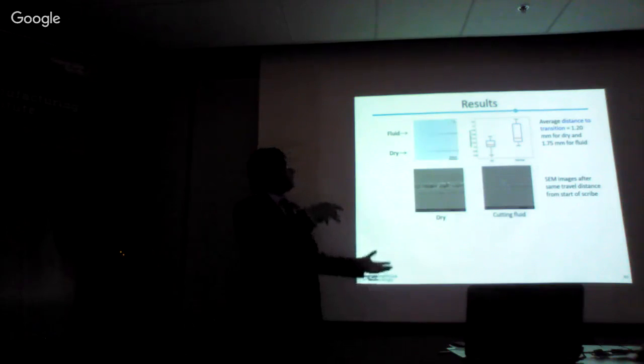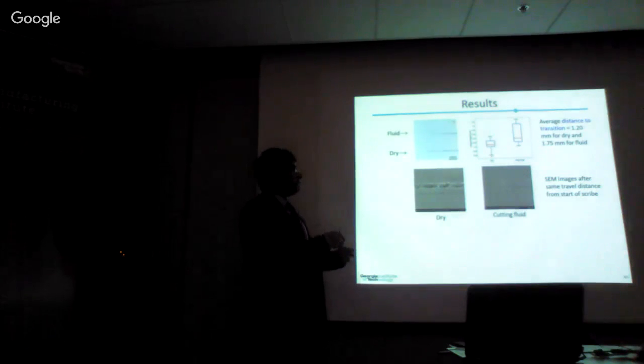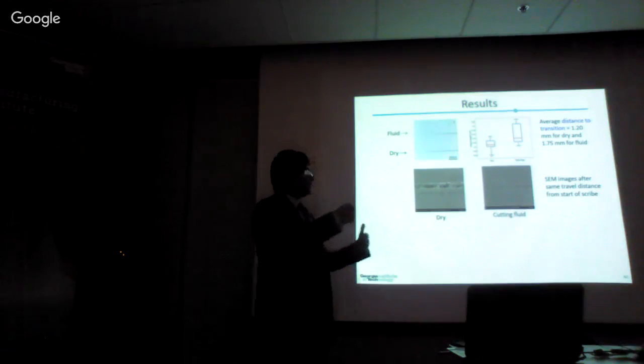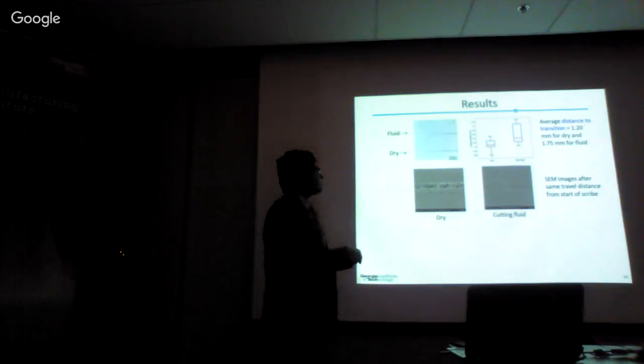If we compare the SEM images of the scribes after the same distance from the start of the scribe using the dry and using cutting fluid, here also we find that for the dry condition there are some cracks appearing on the side, as you see here, radial chevron cracks on the surface. Whereas on the other one, we see that using the cutting fluid there is more ductile mode material removal, not as many cracks.